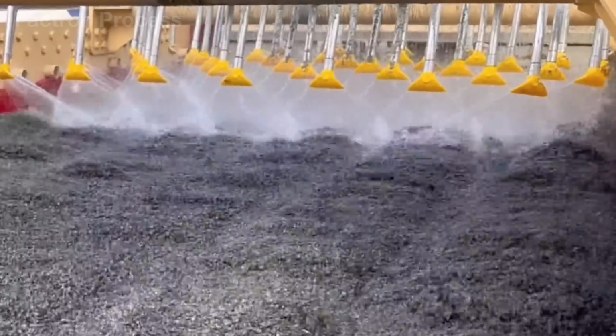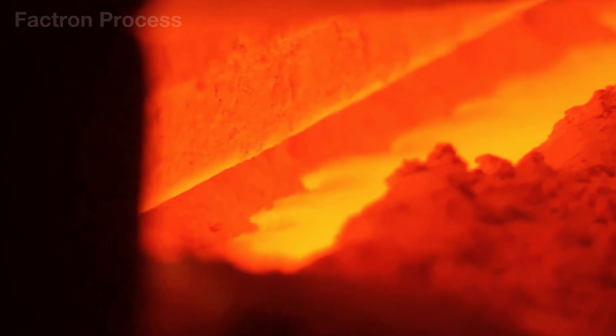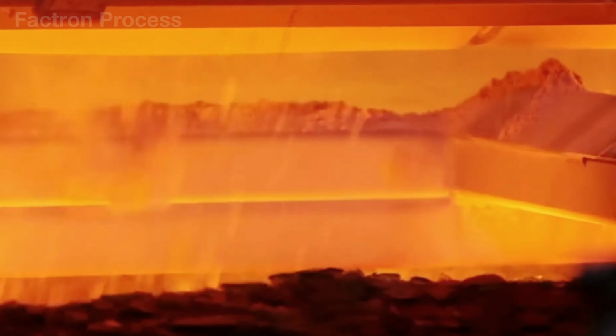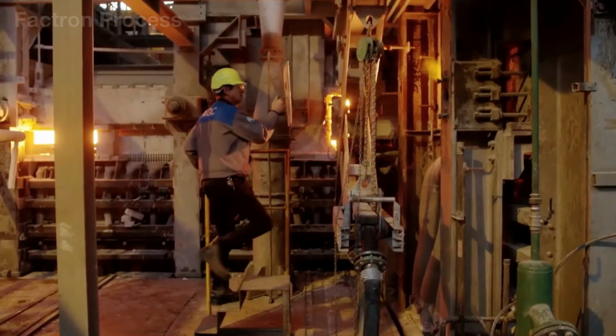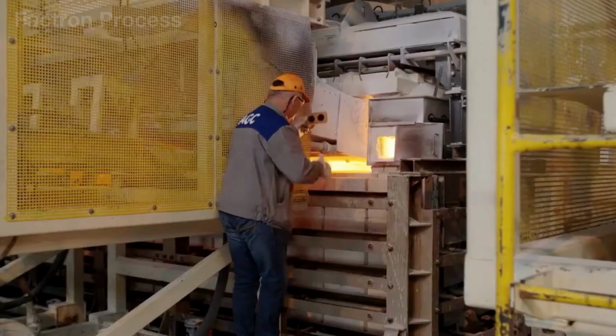The purified silica is blended with finely ground limestone, soda ash, and various additives before entering a continuous melting furnace. Inside, temperatures rise from approximately 1,832 degrees Fahrenheit to more than 2,822 degrees Fahrenheit, and the material remains in a molten state for nearly 50 hours until the glass becomes fully homogenized, free of trapped gases, and ready to be drawn into fiberglass fibers.